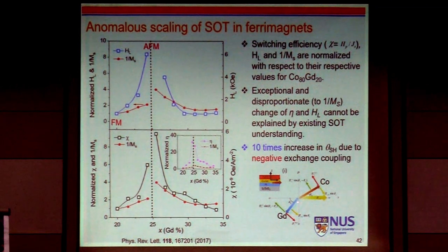It's the more effective one. Then gadolinium follows, which was measured by Kimmel's and Tao and so on, in the early days. But when you have the gadolinium-rich regime, because the cobalt volume is small, when you inject a lot of conduction electrons with angular momentum, the cobalt cannot absorb all this momentum immediately. So that's why the efficiency in this regime is smaller than in the cobalt-dominated regime.